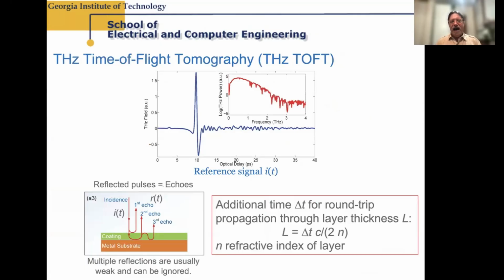Now, just to point out how this works, we send in a signal like this, and we get a reflected signal. For example, here's that example we saw before, a painted coating on, say, metal. We get these different reflections, we call them echoes. And the time delay between the various echoes tells us how thick that coating is. We have to know the refractive index of that layer, or have a good idea, but if we do this experiment across the sample, we can get a mapping of the thickness of that layer. This factor of 2 is because it requires a round trip of the signal through the layer. Almost never do we have to worry about multiple reflections, though they're included here because in some cases they're evident in our experiments.